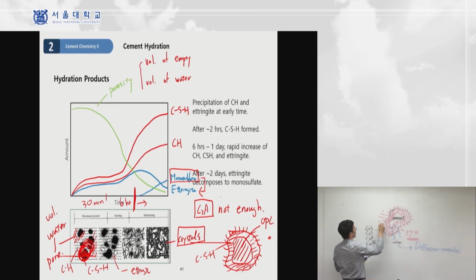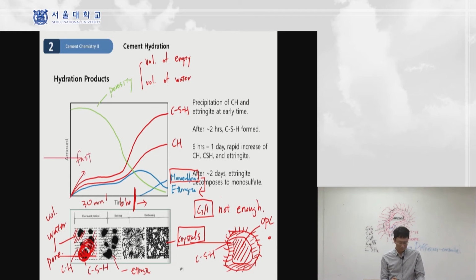And there will be more formation of this calcium silicate hydrate. So eventually, this water region will be filled with a hydration product. That is the reason why at the beginning, the speed of hydration is very fast. But from some point, the hydration process is slowed down because the hydration is governed by diffusion. That means water should penetrate into the calcium silicate hydrate to form additional hydration product, and then the additional hydration product also has to expand to push out this calcium silicate hydrate to occupy this original volume.